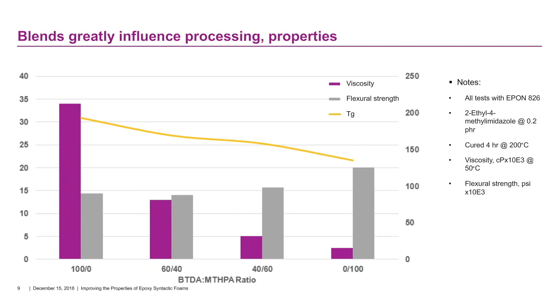Here we show the give and take between putting a blend together and what impact it has on processing, on properties, and some of the downstream performance. You would think that you could simply swap one anhydride for the other and you would be fine and you could carry on with your existing formulation. And that's simply not the case, as demonstrated here. We show a blend of BTDA and MTHPA, so you've got a solid, finely divided particle, and you've got a very low viscosity liquid being put together in different ratios.